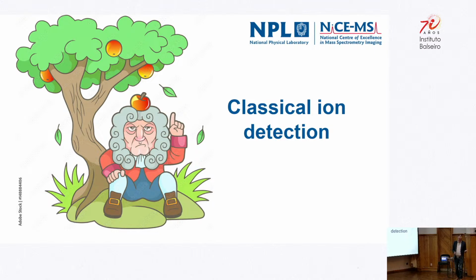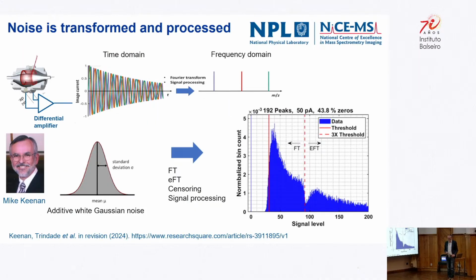So single ion detection, which we have in the time of flight analyzer here, is very nice because in this example here, the apple falls on Newton's head and Newton goes, one apple, I detected it. But it's not like that in an Orbitrap. So in an Orbitrap, the ions are cycling round and round, and we detect an image charge, and that image charge is in this operational amplifier here. We get what's called a transient, and then we do a fast Fourier transform.